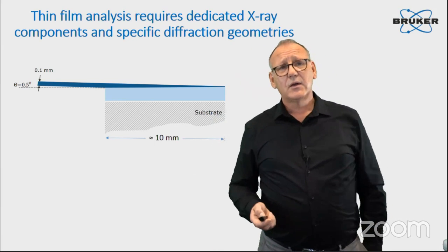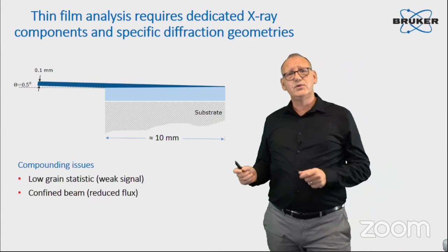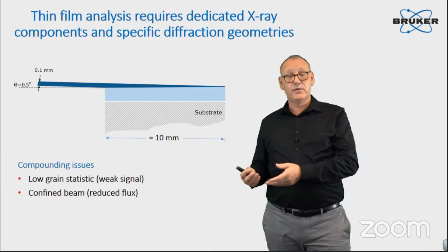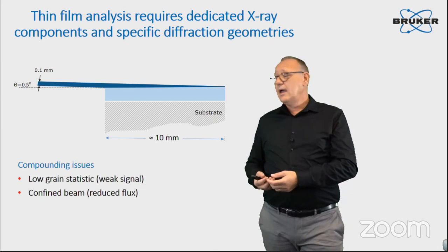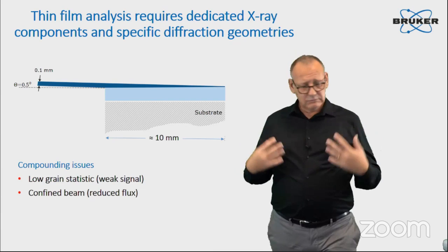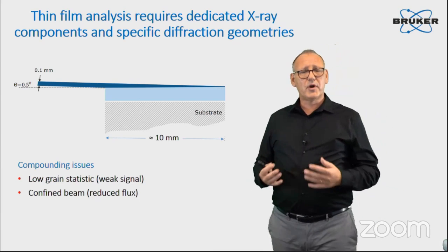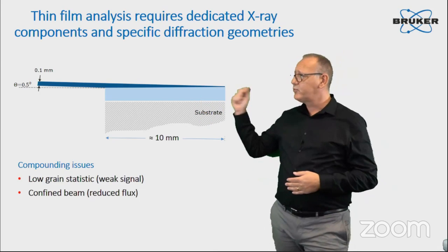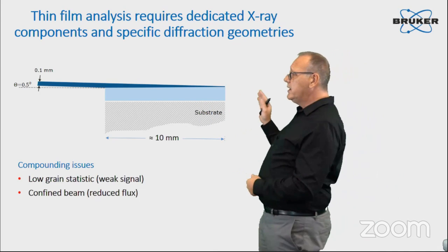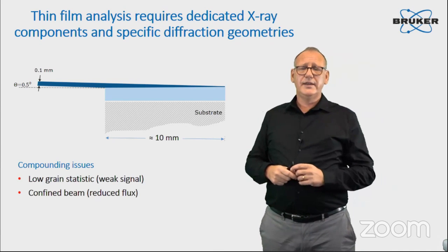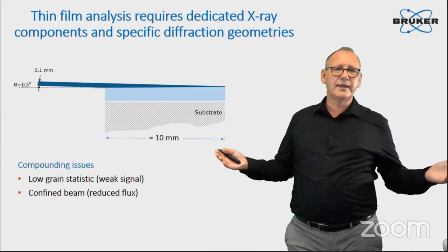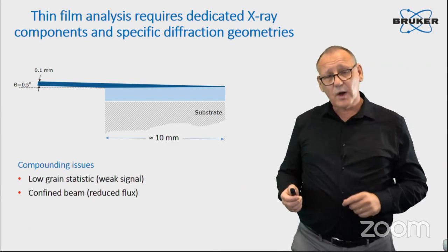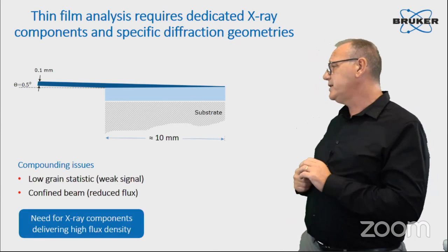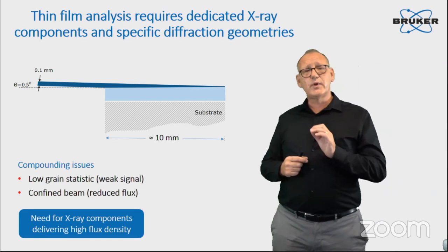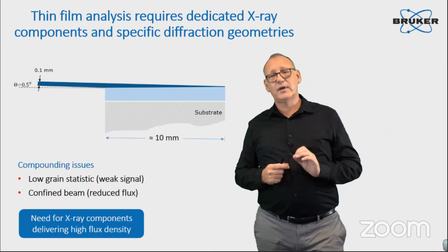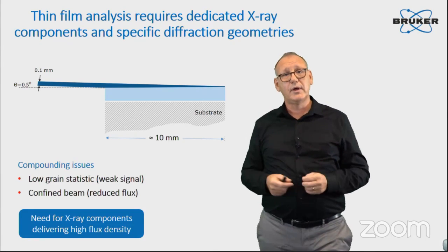So we have here compounding issues. On one side, you have a very low grain statistic that will deliver a very weak signal intrinsically. So you would like to illuminate it with all the flux you can deliver, but the problem is that you have to confine this beam because of this footprint problem. If you don't confine it, you will over-illuminate your sample and you will simply generate more background. You will not get any additional count from your layer. So to have a successful GID measurement, you need to use X-ray components that deliver a very high flux density in order to be able to do proper evaluation.